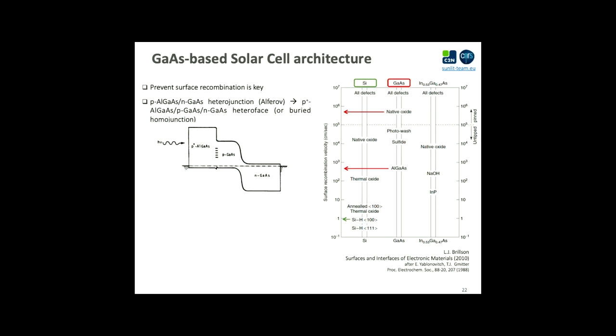Also, the advantage compared to MBE is that you can go at very high deposition rate. And I think Fraunhofer a couple of years ago showed that you can actually achieve something like 100 micrometers per hour, which is really fast.